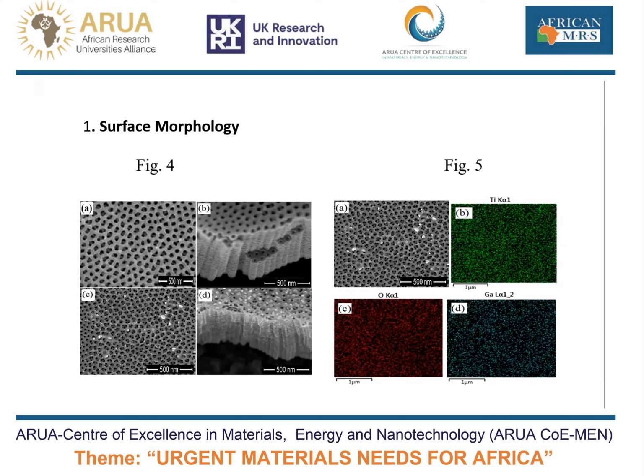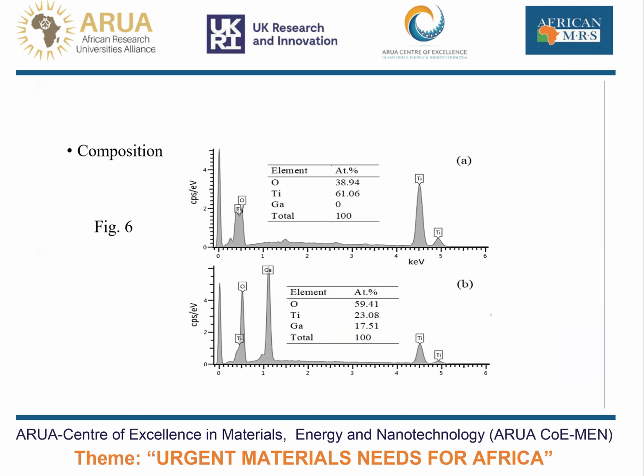Then figure 5 shows the elemental mapping, showing the various elements such as titanium, oxygen, and gallium. Figure 6 is the EDX, showing the elemental composition and the spectrographs of the prepared films. It can be seen that there is no gallium oxide in figure 6A, but for figure 6B, gallium oxide is present because of its decoration on the titanium oxide nanotube films.